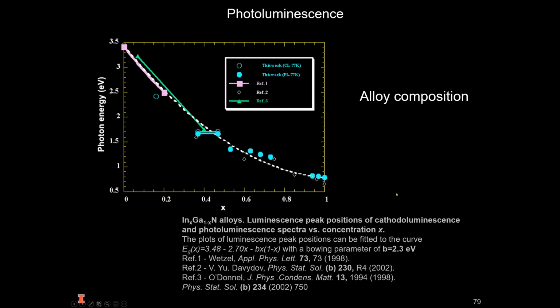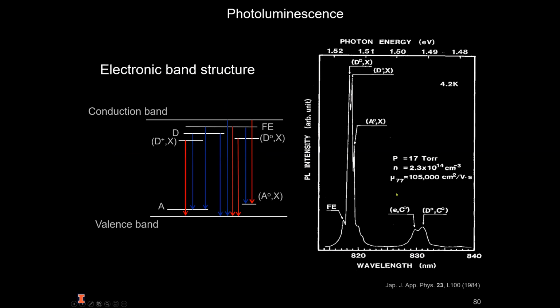In fact, since the energy of the emitted photons will match those of the electronic transitions on the material, photoluminescence can pretty much map much of the electronic band structure of the material, as is demonstrated here for a high purity sample of gallium arsenide grown by MOCVD.